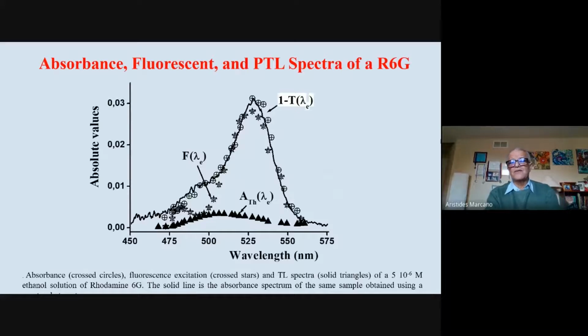I will just show the important thing here. When you do the thermal lensing, the black triangles are the thermal lensing result. It's very small because this sample has a very big fluorescence. And this is the absorbance and fluorescence excitation spectrum that we can get. Then we also measure the transmission of the sample, the one minus the transmission, which is the absorbance, because the absorption is very small. You can actually see that thermal lensing plus fluorescence gives the absorbance. That means the absorbance measured in the transmission experiment splits: some goes to fluorescence, some goes to thermal lensing. And we can see that the thermal lensing spectrum is very different from the total transmission spectrum.